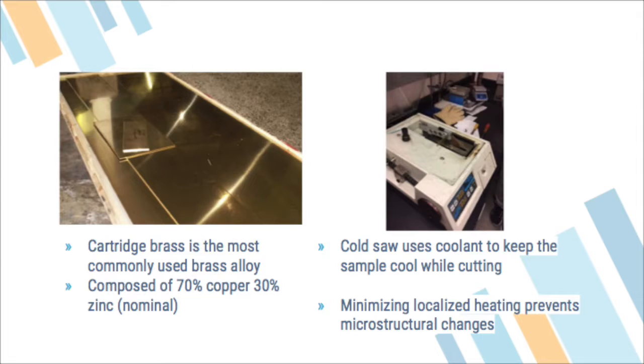A cold saw was used to cut smaller sections from the initial bar in preparation for heat treating. A coolant is circulated over the sample while a blade makes the cut. Speed and feed rates are optimized to allow cutting the samples without damage. Using the cold saw helps to maintain the microstructure created by cold working by minimizing localized heating in the metal.